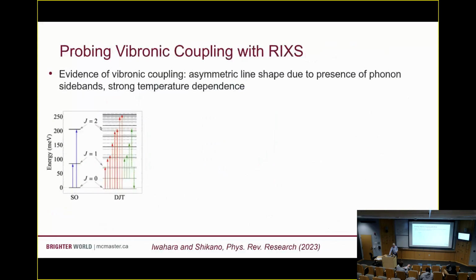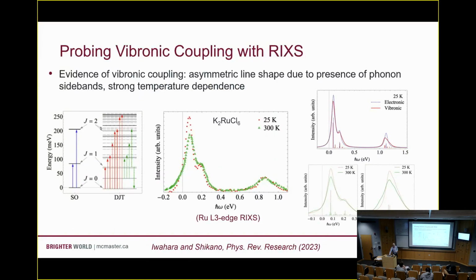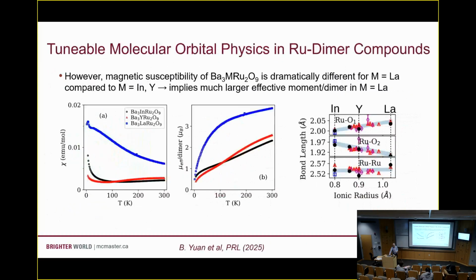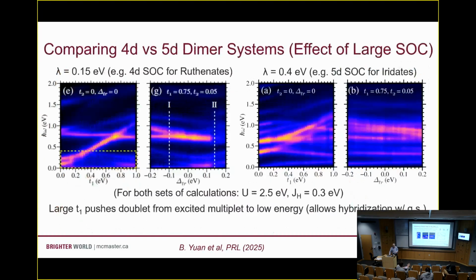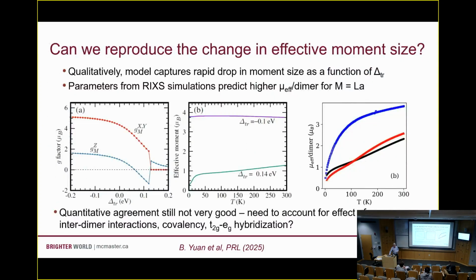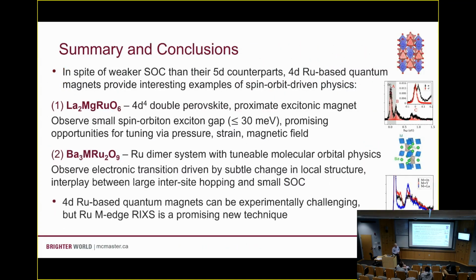What does it mean when you condense the exciton? Is it like if you have a singlet ground state magnet and you apply a field and you can condense one of the triplet states in a Bose-Einstein condensation? Is it like that? Yeah. You're imagining that you're getting these J=1 moments appearing when you lower that energy across the stability point. It's normally non-magnetic. You condense them, so you get ordering of J equals 1 around this Q equals Q naught, wherever the dip in the spin orbit exciton dispersion is.